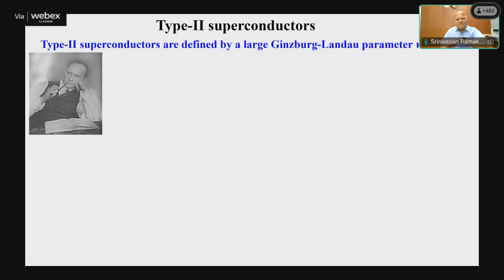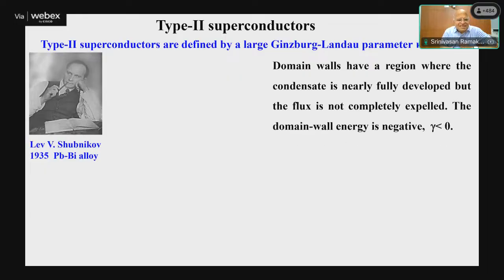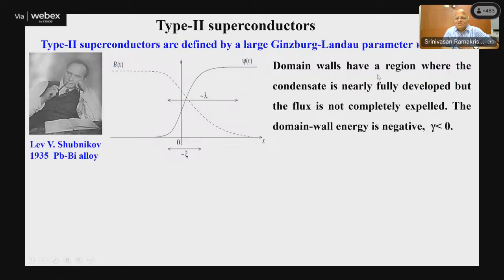So we understand how the type 1 superconductors behave because they follow the Meissner field effect. The magnetic field gets expelled and it goes to the normal state. The type 2 superconductor is a different beast. It allows the field to enter after Hc1. And this was first seen by Shubnikov, so that's why it's called the Shubnikov effect. He worked on a lead bismuth alloy. For the lead bismuth alloy, we have a type 2 superconducting state.